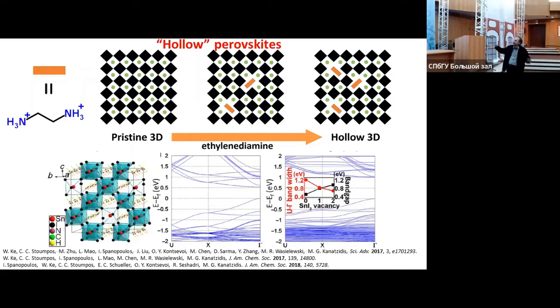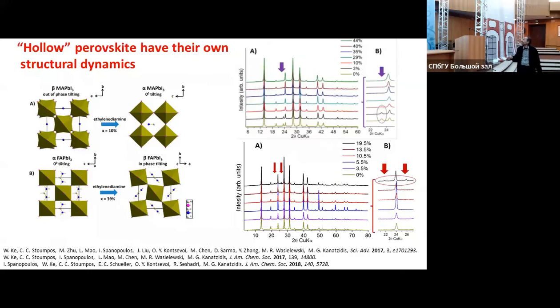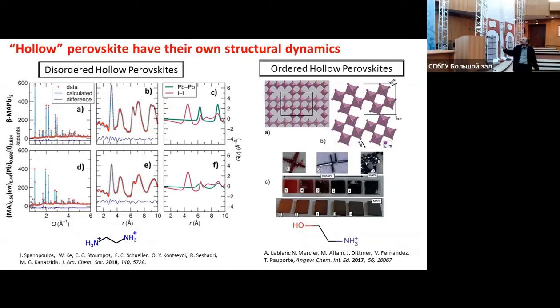And we simply make an artificial crystal structure by removing octahedra from the unit cell. And when you do that and do the band structure analysis, what we see is that missing octahedra will clearly increase the bandgap if you compare this opening here with this opening here. And we made this cartoon model. But to strengthen our argument,